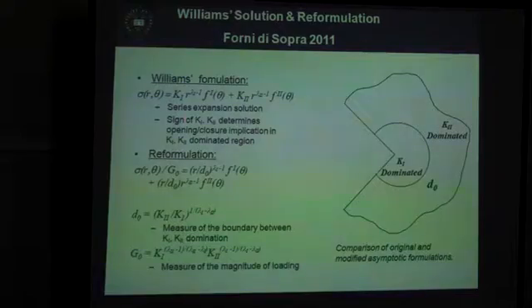But in notch problems, the mode 1 dominates mode 2. So I look for the internal length dimension in this, and replace the K1 and K2 with these other two parameters, d0 and g. And then you can see that d0, which is just this ratio of the K2 to K1, becomes effectively the boundary between K1 and K2 regions.